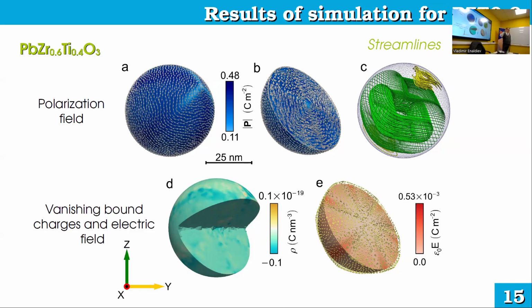Also, you asked about the position of these singular points. Here you can see very interesting stuff. Polarization lines, they're not straight. They're actually deformed by crystal anisotropy. And this anisotropy also defines the position of different singular points. Of course, we calculated the bound charge and electric field for this configuration, and they're vanishingly small. So this divergence of P equals 0 is confirmed.